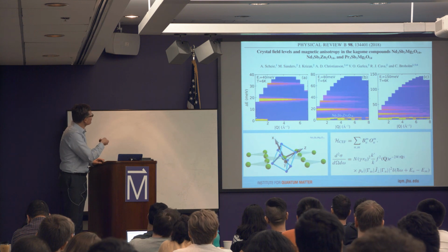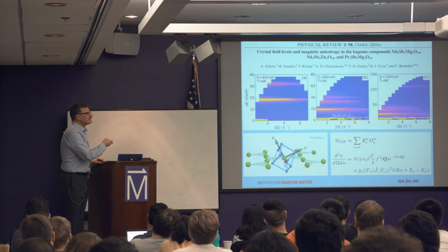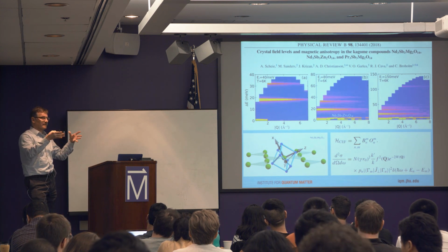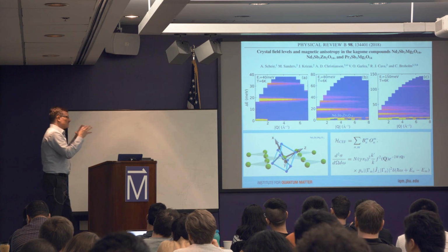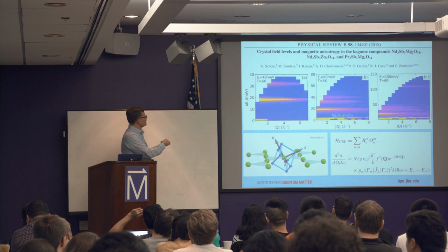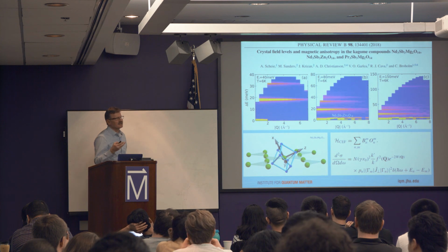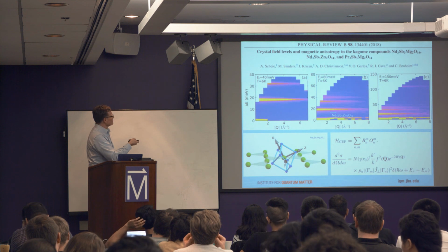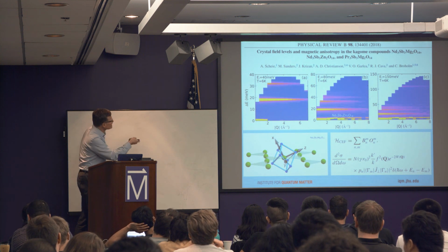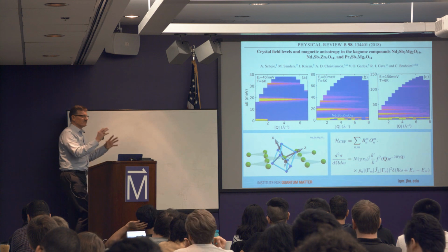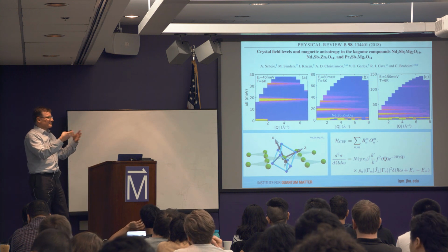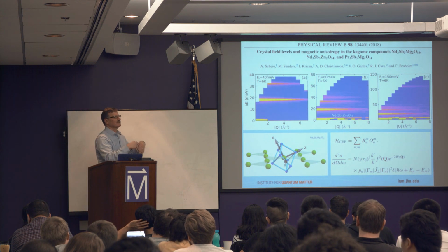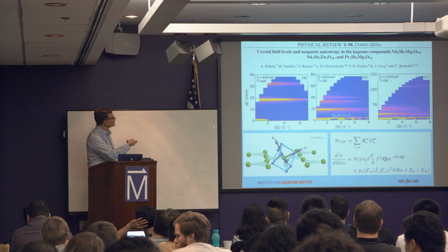And basically what happens is that this line, the elastic line, is a very, very noisy place because, as I said, 90% of the scattering is elastic. So everything which is solid in the vicinity of my sample will contribute right in this line. So I really can't say very much about that line. I think there's some sort of background subtraction that took place here which produced this effect. You can see how it's kind of spotty. I think we had some way of trying to subtract off that contribution, but it's not working so great. So this is something you'll see in this kind of neutron spectroscopy. You'll always see a very noisy elastic line.